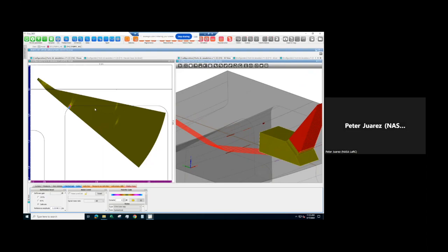And there's a couple of things to take away from this. One, we're doing a sort of an ideal simulation of what the adhesive would look like. In reality, it's actually going to be patchy and different thicknesses, and so it's actually going to be worse than what we're looking at right here. So this is like best case scenario.